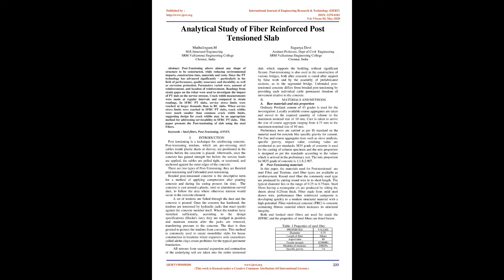Since the PT technology has advanced significantly, particularly in the field of performance, quality assurance, and durability as well as corrosion protection. Parameters varied were amount of reinforcement and location of reinforcement. Readings from strain gauges on the rebar were used to investigate the impact of PT slab on the service stresses. Crack width measurements were made at regular intervals and compared to strain readings.